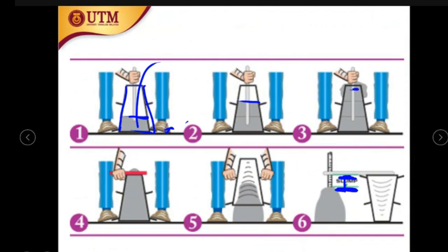When they mixed everything, I asked them, is it workable? In your opinion, what do you think? They said, oh, it is okay, it's slurry, it is okay, and it's mixed well in the mixer and everything. Then when they did the slump test, the slump was very low, only about 10 mm. So basically, we cannot tell whether the concrete is workable or not just by using our eyes.